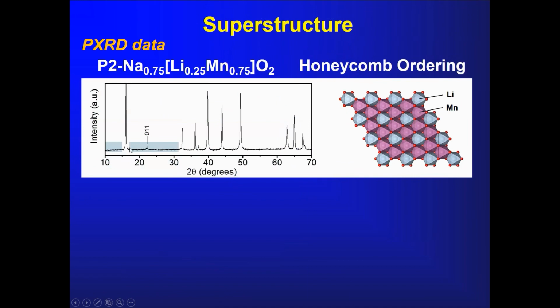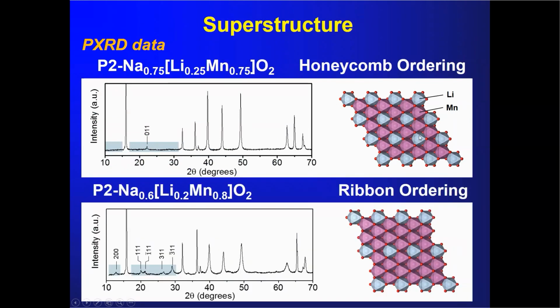The 0.25 compound, this is a powder diffraction pattern for it. It has the characteristic feature, you see it here, of the honeycomb superstructure, and it's represented here. Here's a bit of a clue to what's happening, because in the case of the 0.2 compound, small composition change, it has a different superstructure, one that we call a ribbon superstructure. You contrast these two. This is the honeycomb around the lithium. Here you see these ribbons, represented by the purple shading. So it's a different arrangement of ions in the transition metal sites, a different superstructure. And this superstructure is to a large extent at the heart of suppressing the molecular oxygen.